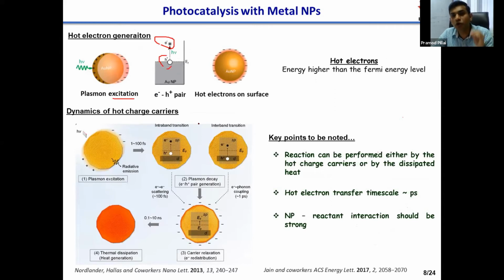So now, in order to do some catalysis, you need to extract these electrons and holes efficiently from the core. Otherwise, they will recombine. And the dynamics of this hot electron chemistry is very, very fast. So this is what is summarized in this figure. I will not go into the detail, but the bottom line here is that within a few picoseconds, something like 1 picosecond, these hot electrons can recombine to form heat. So this means you have very, very limited time to take these hot electrons from the nanoparticle to perform various chemical transformations. So this is a challenge in the area of photocatalysis.